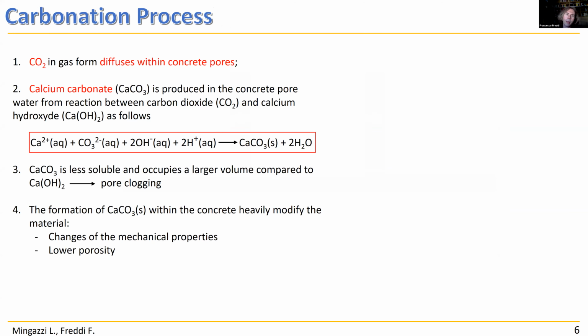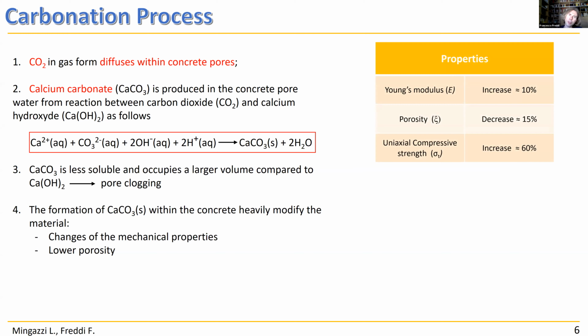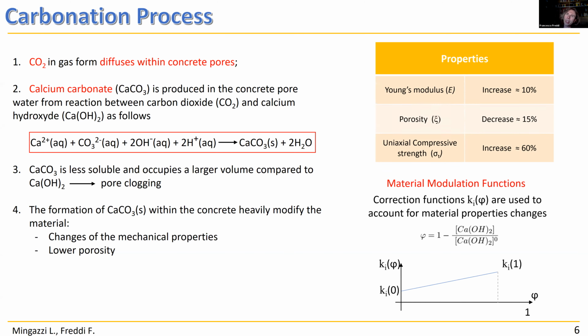Some chemistry. This is the reaction. So CO2 reacts with the calcium hydroxide and calcium carbonate is produced within the concrete pore. A secondary effect that appears within concrete is pore clogging, because calcium carbonate is less soluble and occupies a larger volume compared to the calcium hydroxide. So there is a lower porosity in the element, and there are also changes in the mechanical properties of the concrete itself. In particular, there is an increment of stiffness and an increment of strength. These variations are taken into account in the model.